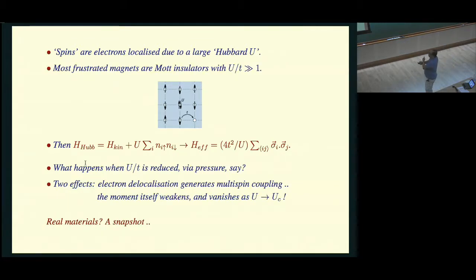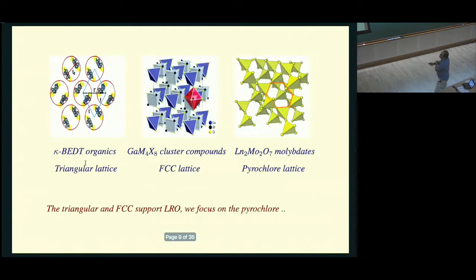Well, there are multiple examples, in fact. The most famous, well-studied examples come from the 2D organics, the triangular lattice based on the BEDT family, where both physical pressure and chemical substitution of bromine from chlorine, etc., can metallize what seems to be a 120-degree ordered Mott insulator. Less studied are 3D variants, the FCC lattice, which again is ordered. I mean, despite the frustration, there is a degree of residual order that one observes in this. For me, the case would be the pyrochlore lattice, where there is no order at all.